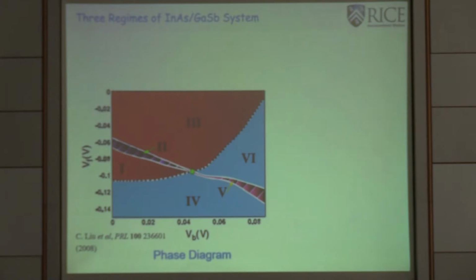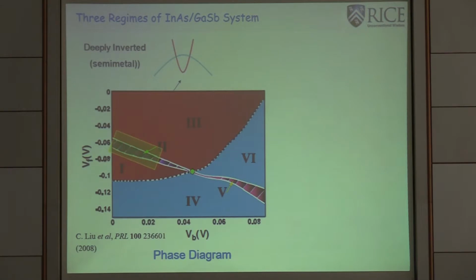So in detail, we can divide this phase diagram into 3 different regions in terms of the density. The first region is the so-called deeply inverted region. Basically, you have high density of electrons and holes. Although they are equal in number, the system is not really insulating, rather it's semi-metal because the energy gap is pretty small as compared to the other parameters. Therefore, you basically have a poor metal or semi-metal like this.